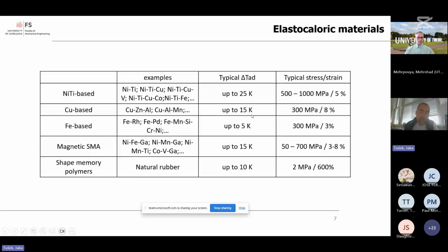The story is different in polymers. The background is not martensitic transformation, but rather the reorientation of polymeric chains. Polymers have very low transformation stress required, but also very significant strain. So it might be a bit impractical that the elastocaloric device requires 600% of strain, but the elastocaloric effect can be quite decent, up to 10 kelvins.